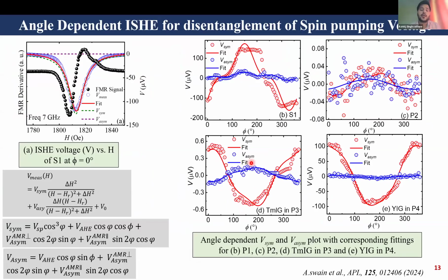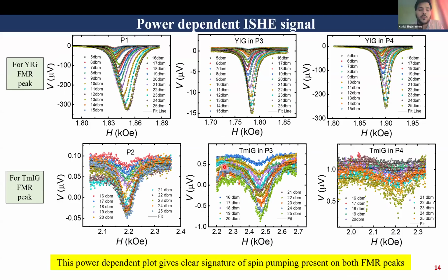This was then characterized angle dependently with the change of azimuthal angle, where at each angle we have plotted the V symmetric and V asymmetric after fitting with the Lorentzian equations, having a symmetric and an asymmetric component. In this plot, you can see a significant rise in the V symmetric signal as compared to the asymmetric signal because of the component of the VSP present in the V symmetric signal. So VSP here denotes the spin pumping potential that we get from these signals. This VSP shows the high spin pumping present in our system, which was later confirmed with the power dependent plot, which increases with the power for all the samples that we have taken.